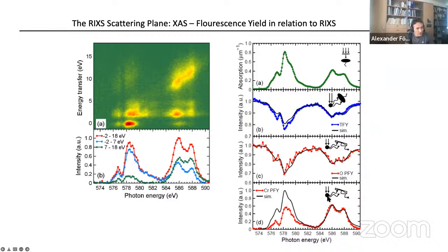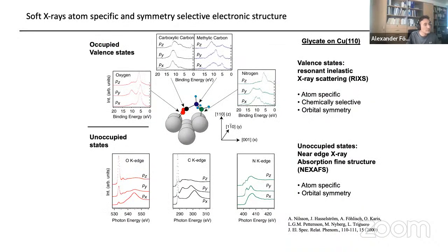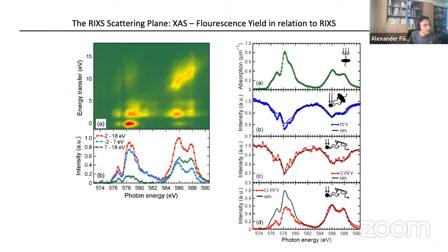And therefore, for your measurement in fluorescence yield, by shining light onto a solid and then measuring fluorescence coming out, you can get rather good results in normal in, grazing out, but you always suffer a deviation from the ideal situation. So whenever we measure X-ray absorption with these types of techniques, we have to be very careful, and we should not lightheartedly assign relative intensities to true absorption strength. But even though we have a deviation from the ideal case of absorption from the Lambert-Beer law, we still get very good signatures of where the absorption states are, even in these partial yield methods. But everybody who is using this should get acquainted with the issue of X-ray absorption measurements and these aspects of what we call self-absorption.